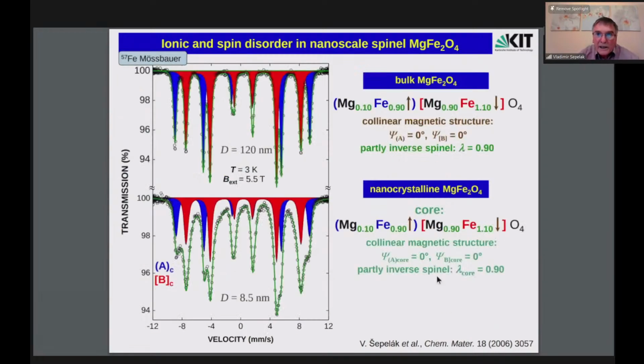And then if we look at low temperature Mössbauer spectra taken in an external magnetic field, now the iron cations in tetra positions and octa positions, the subspectra are clearly resolved, and from the intensity of these two subspectra we again calculate the degree of inversion, and for bulk material it is 0.9. It is the concentration of iron on tetrahedral sites, and of magnesium on octahedral sites, we see 0.9. And from the ratio of the second to first line, we can even calculate the degree of collinearity, the so-called spin canting angle. And we see that in the case of conventionally prepared material, our spins are collinear, but antiparallel oriented on A and B sites.